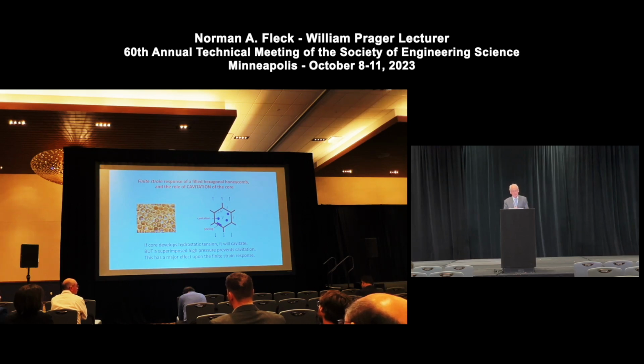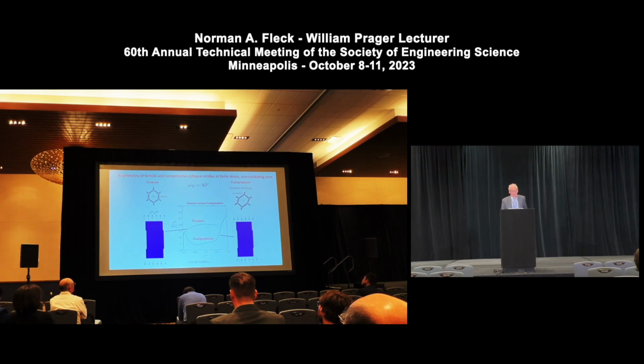So the added physics, when you do the experiments on these lattices, is it's very hard for the core to maintain constant volume if the cell wants to expand, because peeling, cracks can take place, cavitation can take place. So there's this notion of cavitation of the core being important. To show that, let's just deal with the compressive case. Here is a non-cavitating core. So I'm going to keep constant volume. I've got omega is 40 degrees. I have this strongly softening behavior.